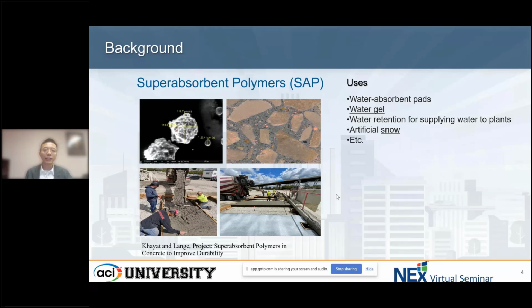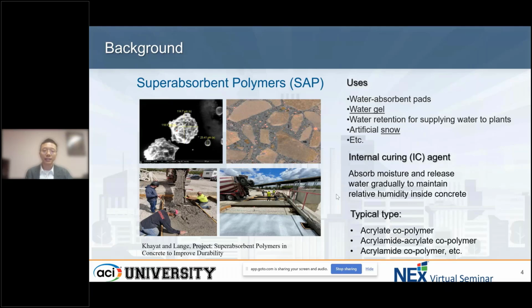And why do we use it in concrete? Because it can be used in concrete as an internal curing agent. It absorbs moisture inside concrete when it is in fresh state and releases the water gradually to sustain the relative humidity inside the concrete when it gets hardened. In this way, it can significantly reduce the shrinkage of the concrete, and we all know the shrinkage of concrete is a very big problem. It induces cracking and thence reduces the strength and durability of the concrete.